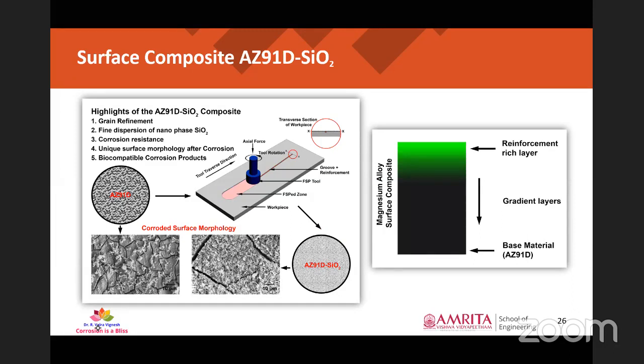The highlights of this composite include grain refinement in the friction stir processed zone. Second is fine dispersion of nanophase silica. Third is the corrosion resistance of magnesium alloy has improved to a great extent. Fourth is the unique surface morphology after corrosion phenomenon that has significantly contributed towards corrosion resistance of the material. And fifth is biocompatible corrosion products, which is very similar to the thing that we have discussed already.